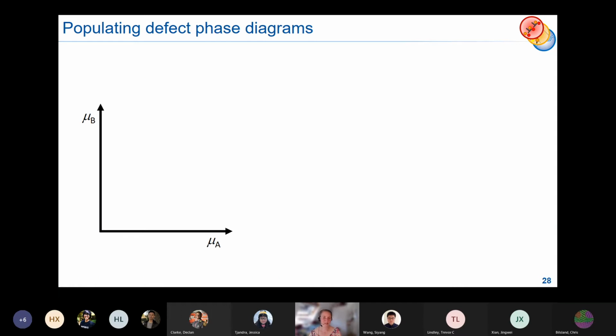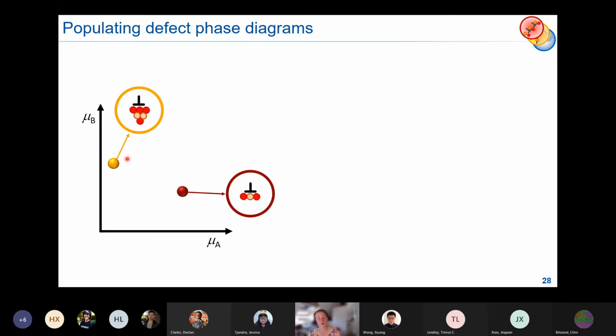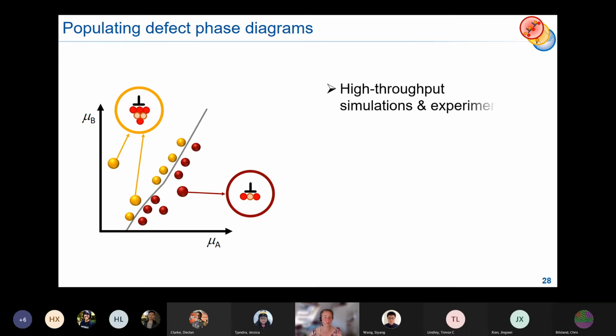And then we need to think about actually doing this, and this is where the problem comes in. There are now a lot of variables or a lot of different defects that we need to look at for two axes, for example, the chemical potential of two alloying elements. So what we think you have to be doing is what you would do in different phase diagrams as well. You have to go and look into your alloy, look at maybe having one defect structure at one point and then having a different defect phase at another point. And then we would have to keep looking for other points and look for the boundaries in our phase diagrams, just like you would do for a normal phase diagram.